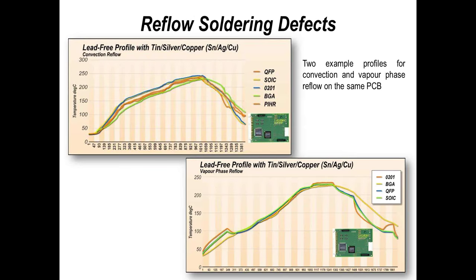So what I show you here is just two thermoprofile graphs that I've picked from my library, and we see convection, we see vapor phase, and we can adapt a profile for vapor phase to look like a convection profile if that's what you want to do. Traditionally, we would have difficulty in preheating and reflowing and having a nice steady profile. Here we have a relatively steady profile with small delta T's.